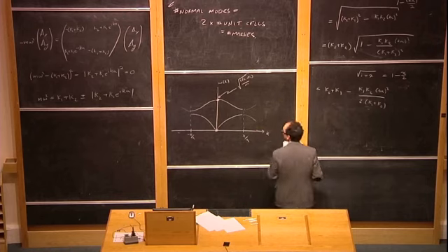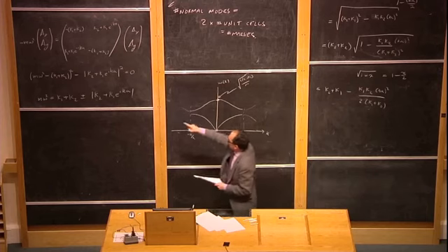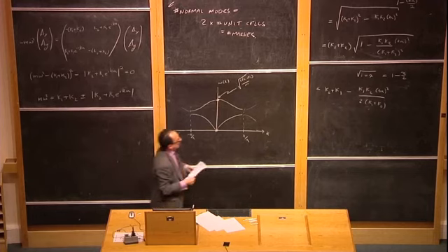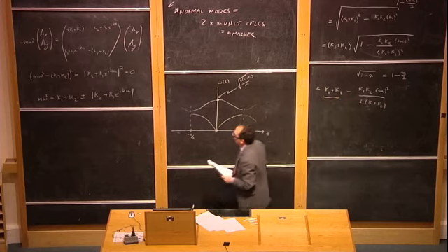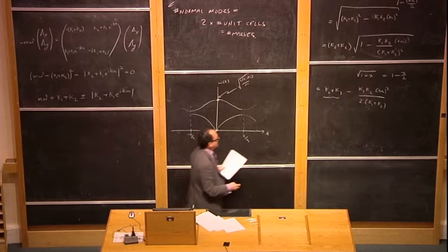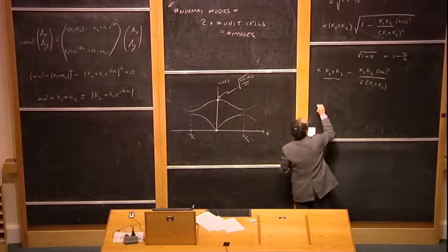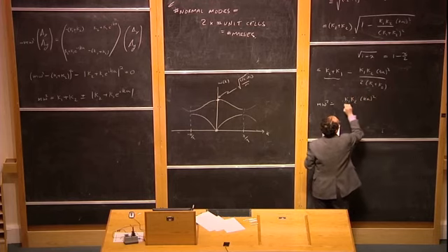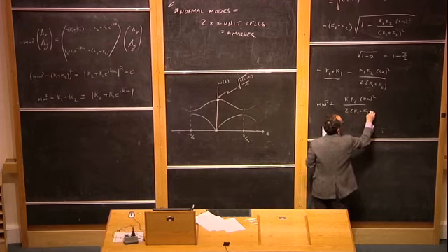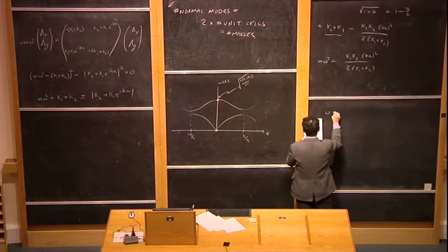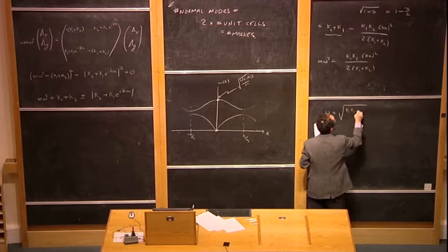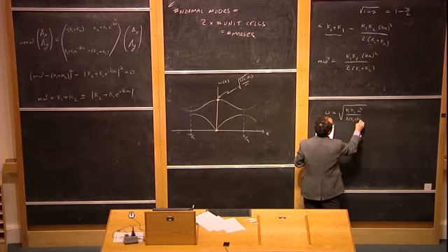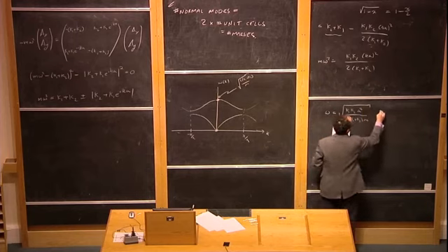So, all right, if I plug that in here, we see that the kappa 1 plus kappa 2 with the minus solution cancels this, kappa 1 plus kappa 2 also will cancel this, and we'll end up just getting m omega squared equals kappa 1 kappa 2 Ka squared over 2 kappa 1 plus kappa 2, or equivalently, omega is the square root of kappa 1 kappa 2 a squared over 2 m kappa 1 plus kappa 2, absolute k.